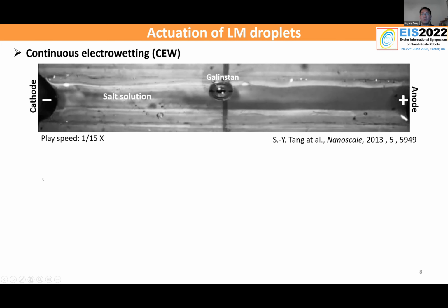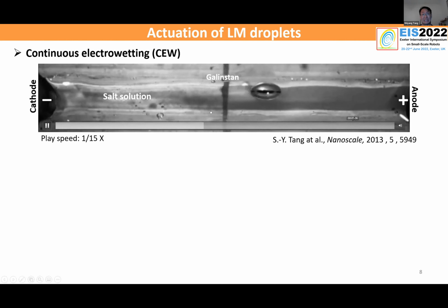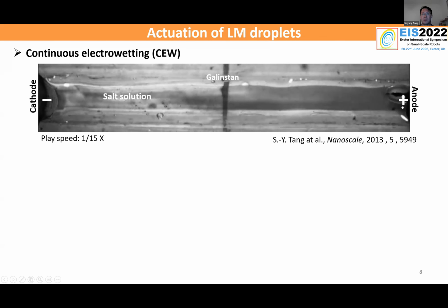When I apply the potential gradient, I found that the droplet is able to migrate towards the anode at a very high speed, approximately 10 centimeters per second, because this is high speed footage, so the actual speed is relatively high. So why is this happening? This is not because of electric forces, because the electric field is super low if you just divide the 10 volts by 10 centimeters. So the actuation is actually caused by the electrowetting or alternatively the Marangoni effect.